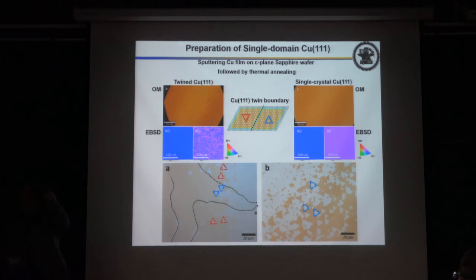Okay. The second question is about this boron nitride grown on metal. Sorry that I didn't catch why it is necessary to grow boron nitride on metal instead of on sapphire. Because we are unable to grow on sapphire. So we use copper, which can be considered a little bit of a catalyst, but in this case, it also depends on the solubility of the material in the metal. For boron and nitrogen in copper, the solubility is very low, so the growth is self-limited and will grow only one layer. But for some other metal like nickel, the solubility of boron and nitrogen is higher, so if you grow the material on nickel, you typically form multilayer.